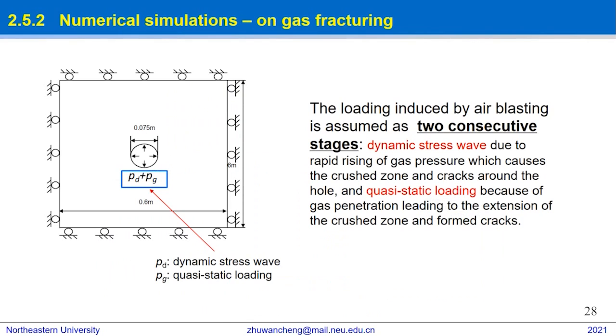This figure shows numerical model setup for high-pressure air blasting on concrete specimen. In our numerical simulation, the loading induced by air blasting is assumed as 2 consecutive stages: dynamic stress wave due to rapid rising of gas pressure which causes the crushed zone and cracks around the hole, and quasi-static loading because of gas penetration leading to the extension of the crushed zone and formed cracks.